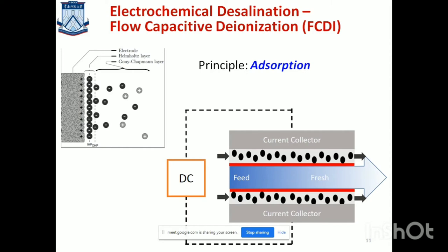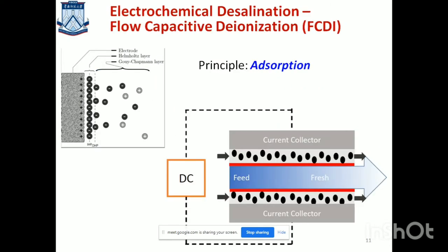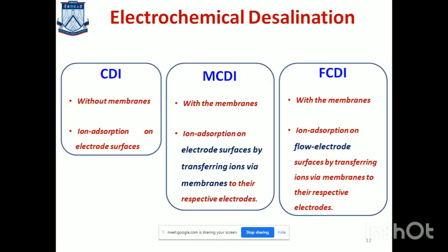Okay, the second work, in JMCA. Here we confirmed that using the redox electrolyte, we can run a continuous process where the sodium ions and the chloride ions move to their respective electrodes. The salt concentration increases in the redox stream, and nothing else happens. On the right side, in the graph, the NaCl concentration was reduced from 7000 ppm to nearly 500 ppm. Of course it is very good that 7000 ppm salt water has been reduced to 500 ppm. Still, we wanted to enhance the salt removal rate.